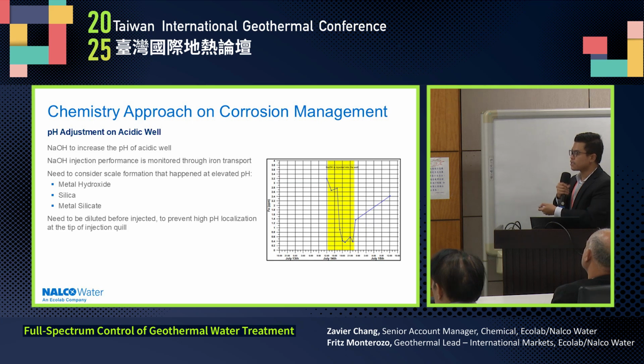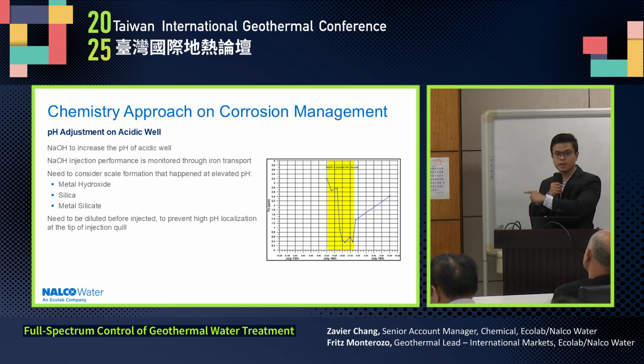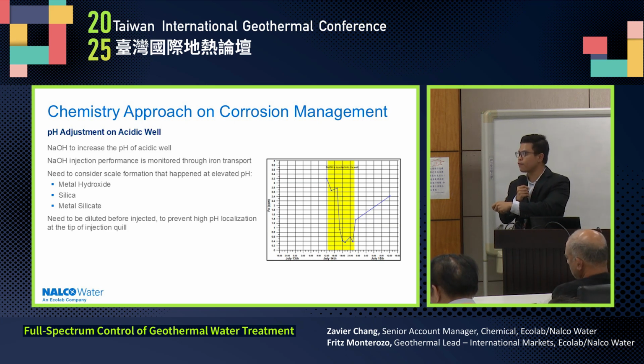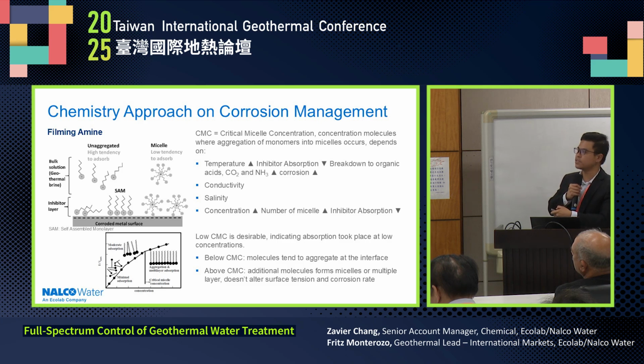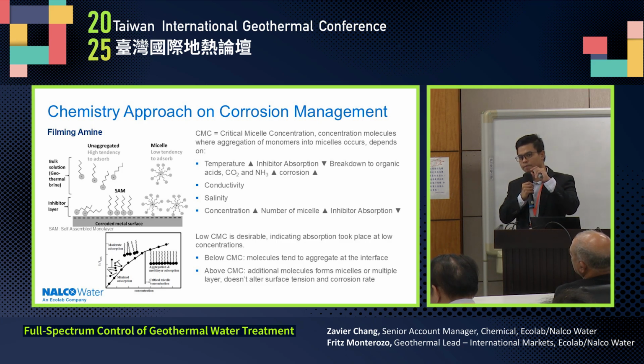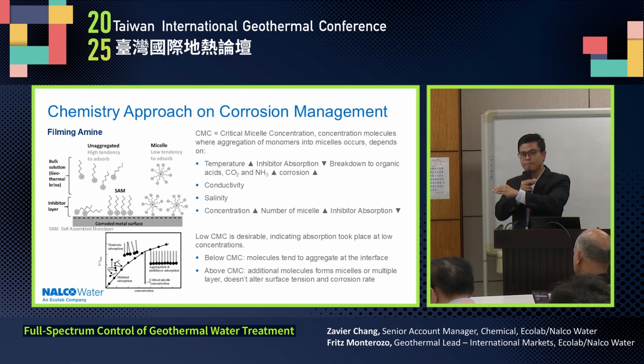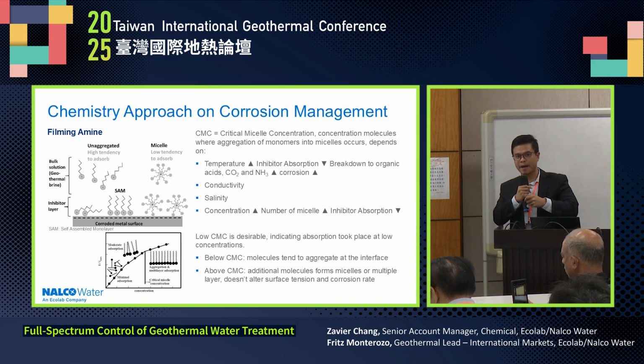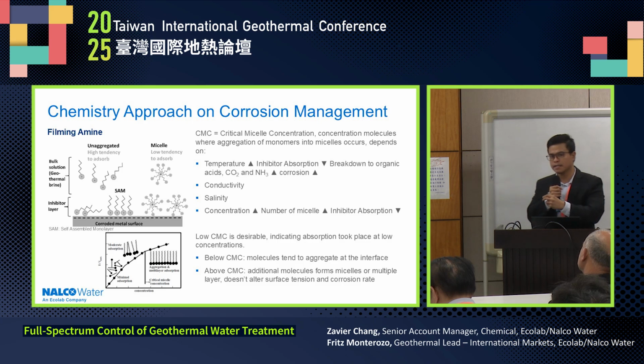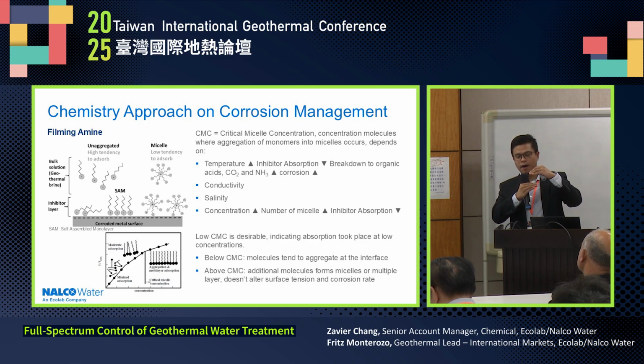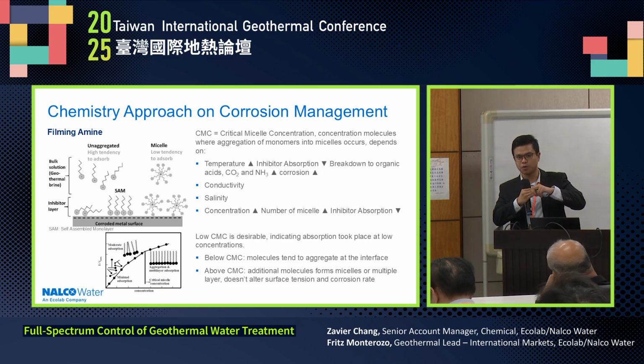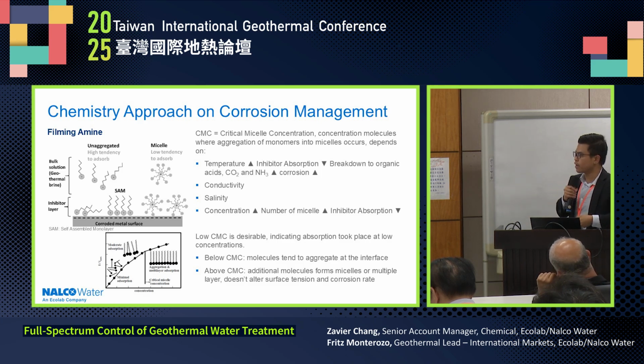Some of the approaches that we use, same with how we address silica, are adjustments in terms of pH, but now we're using caustic. We raise the pH of the well to become less acidic, but the drawback is you are introducing another problem, which is scaling. We know that scales are pH dependent. Another one is the use of filming amines. You dose corrosion inhibitors or filming amines in your system, and it creates a passivation film on the walls of your pipe. The benefit is that it prevents corrodants from getting to the surface of your pipe. It's a protective layer to prevent or lower corrosion rates.